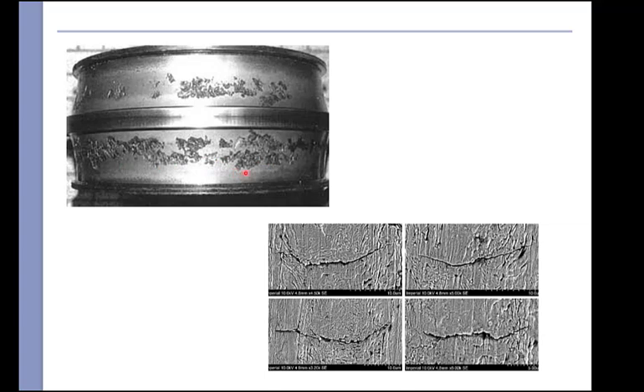If you section and look below the surface, you find that if the surface is up here, you get these cracks that form below the surface. They have this shape such that they turn up towards the surface. Once they reach the surface, a chunk of material spalls off. And that leaves all these pits behind that ruin the rolling contact surface. So that's a mechanistic explanation based upon the maximum shear stress that occurs below the surface brought about by contact stresses.